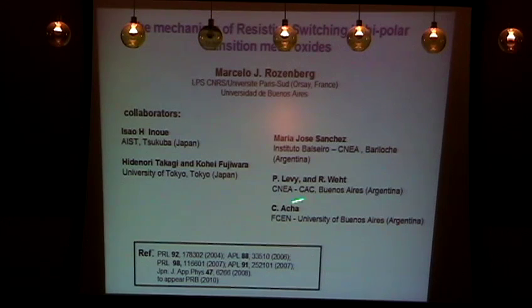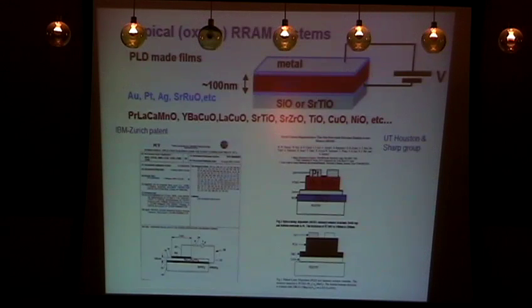Okay, so here you have a set of references of the different work that we've done in our efforts to model the effect of resistive switching. We've seen resistive switching systems yesterday, just to remind you, because this is the first talk. The typical RRAM system has two metallic electrodes in a capacitor-like structure with a dielectric, which is a transition metal oxide. For transition metal oxides, the big surprise is that almost anything works.